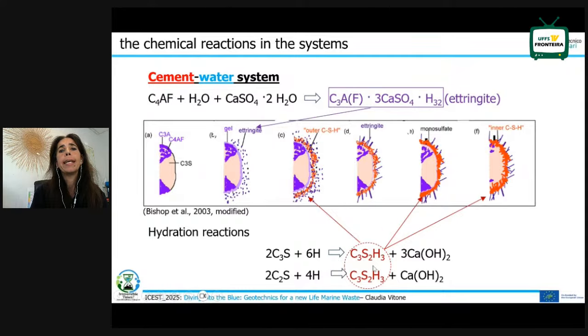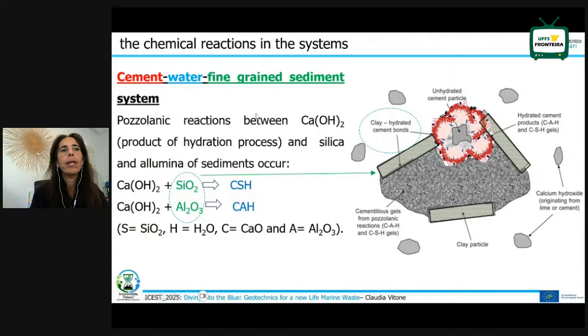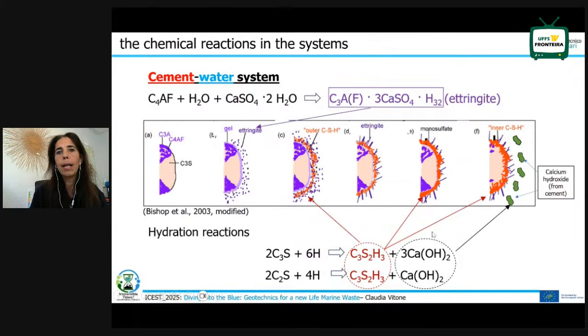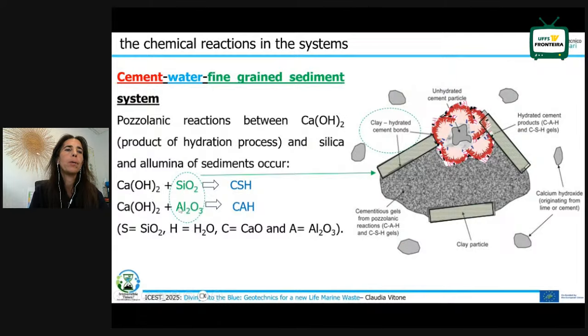So we have calcium silicate hydrates, and these calcium silicate hydrates, when we mix a clay or fine-grained sediments, react with the silicate and the aluminate within the clay materials, so that we have the formation of portlandite. The portlandite, so the calcium hydroxide, reacts with silicate and aluminate to form other products of calcium silicate hydrates. So this means that pozzolanic reactions are occurring. These are standard chemical reactions between cement, water, and fine-grained sediment systems, so without shells.